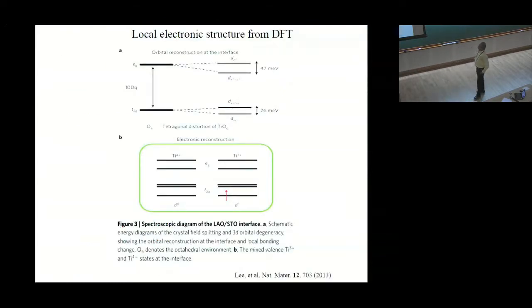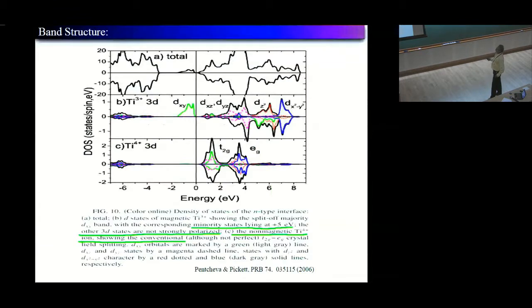Okay, so this is where the theory starts. This is a very simple band structure. It's two-dimensional. Only one band is two-dimensional. In the t2g sector, you have to put one electron there. So dxy is the one where you put the electron in. That's what the band structure also suggests, that there is a dxy band which has very small weight at the Fermi level.